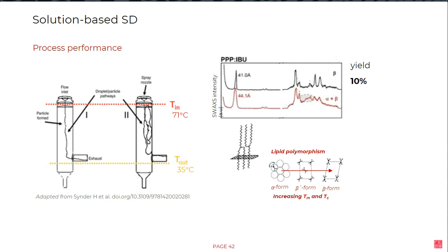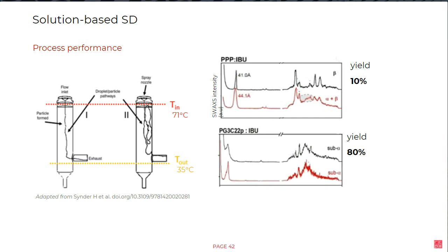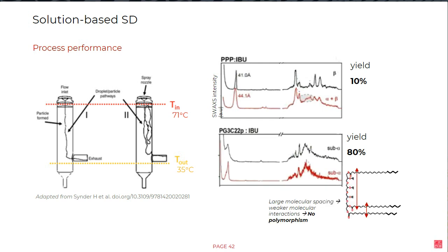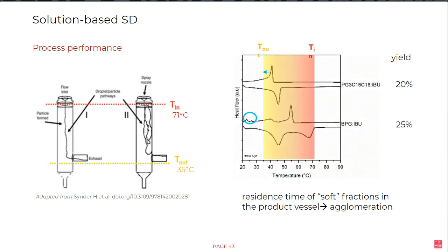On the other hand, PG3 doesn't have any kind of polymorphism, so melting and crystallization temperatures are very close to each other. And finally, we can use this simple DSC analysis to predict some issues that might happen, like how close the recrystallization is to the outlet, or if there is existence of low recrystallizing fractions in the material.